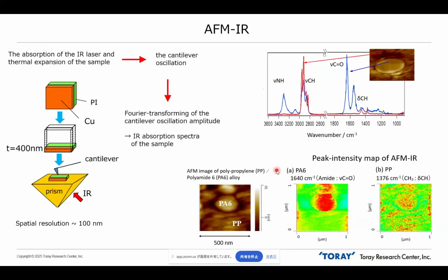Then to know the more detailed chemical structure, we try to use this technique, AFM-IR. In this technique, an infrared laser is irradiated to the specimen. Then thermal expansion of the sample is detected by the needle-like cantilever. Then finally, we can get localized IR absorption spectra.